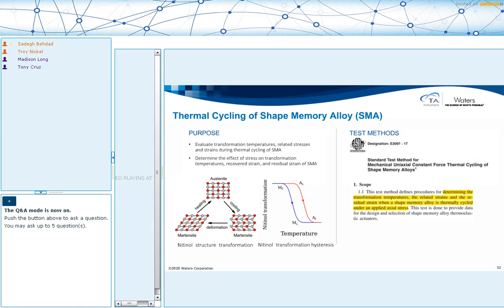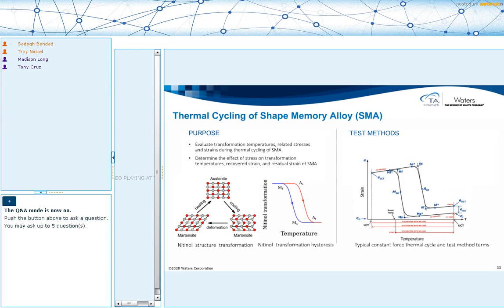So looking at this graph, you can see that there is some hysteresis every time that you go through this cycle. And what we are trying to do by leveraging the standard is determine how much residual strain there is for one run, one cycle of that, and what are these 4 thermal onset points. So Mf, Ms, and As and Af, which are the start and the finish of formation of each of those two phases. The way the standard recommends to do this test is that first you will start here at the